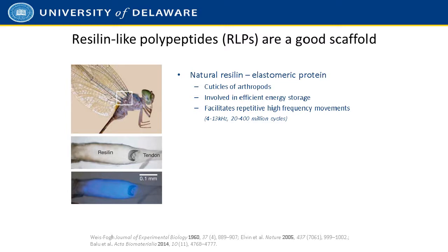And even over the short lifetime of an insect, that's important because wings vibrate at, and sound-producing organs vibrate at, extremely high frequencies. The resilin is naturally fluorescent, as is shown in the bottom image from the tendon of a dragonfly, and it allows us to easily identify where our resilins are located.